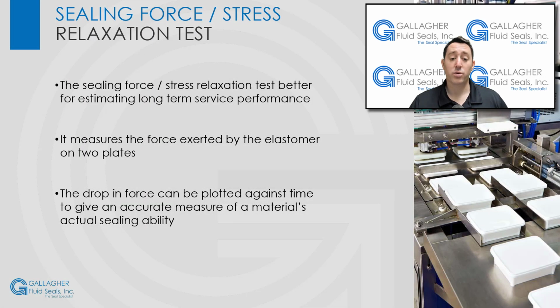The sealing force or stress relaxation test is a much better test than compression set resistance for estimating long-term service performance. It measures the force exerted by the elastomer on two plates. The drop in force can be plotted against time to give an accurate measure of a material's actual sealing ability.